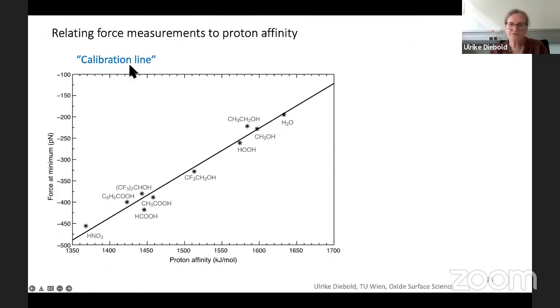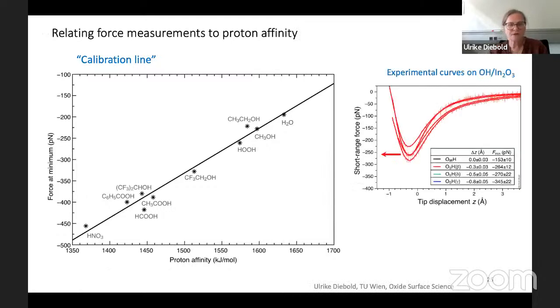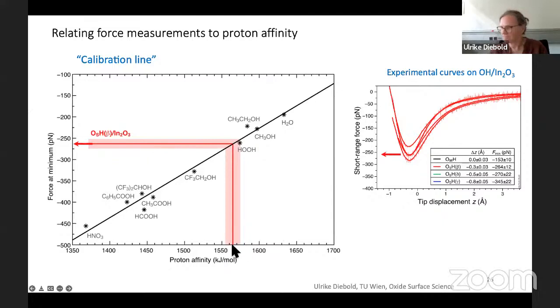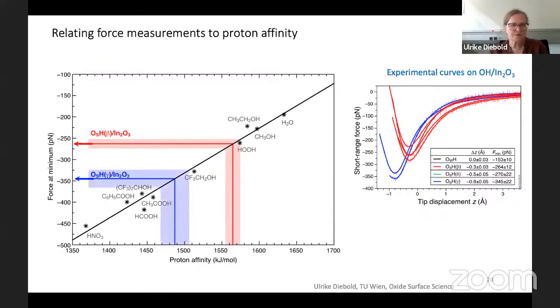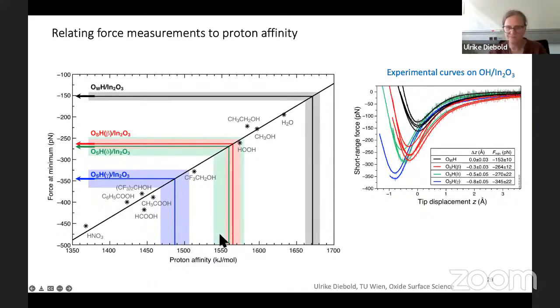So now we do something that's quite brave. We say, okay, we have the force minimum on our surface hydroxyls. This here would be at 250 piconewtons. So 250 piconewtons, then according to this would be this proton affinity. Okay. Then we can do that for the blue curves. And then we would have a proton affinity that's a little bit closer to this acetic acid, so a little bit more acidic than this one. And then we can do that for all of the others, right?